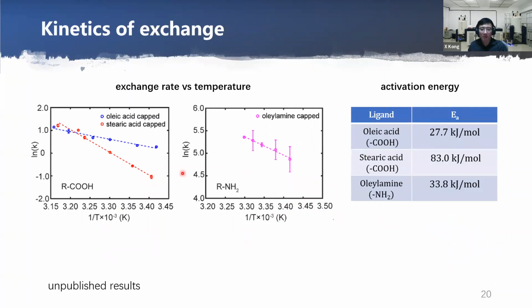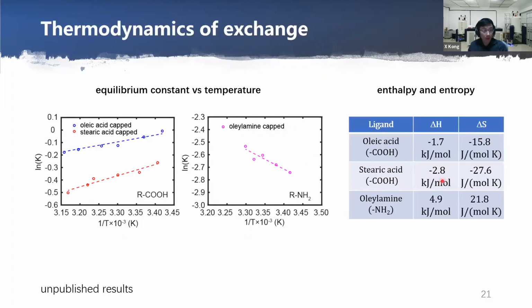So we used this PGSTE to measure the ligands with different chains and different functional groups, for example, the carboxylates and the amines. We can obtain the activation energies for the study of the kinetics. We can also obtain the equilibrium constant, measure it versus temperature, and then get the thermodynamics of the exchange, and also obtain the enthalpy and entropy changes.